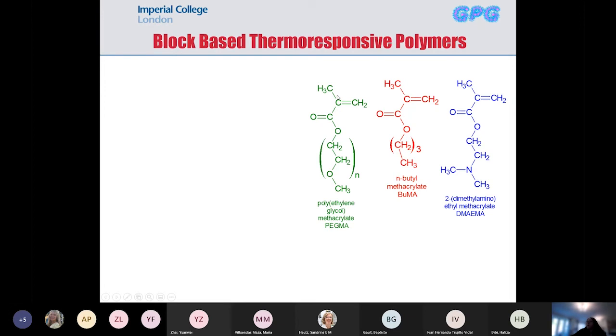So we use PEG as the hydrophilic component. PEG methacrylates can be thermoresponsive, as we'll see later on, but the one that we use is at much higher temperatures. So we use dimethylaminoethyl methacrylate as our thermoresponsive component. We've made polymers that were ABC triblocks, so they had three different blocks. With B, we have the hydrophobic component, with A, the PEG-based monomer, and with blue, the thermoresponsive one.